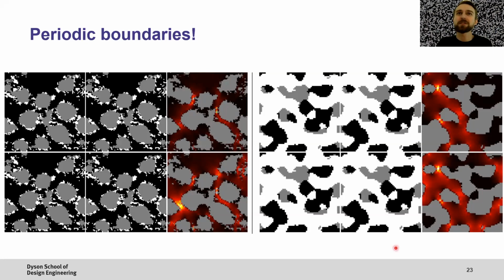So you can just about see, to those who have looked at flux maps before, the top is with the boundaries. In all cases, this is the same microstructure, okay? These 6 are the same microstructure. And I put a matrix of them so you can see that what comes off the right appears on the left and what comes off the bottom appears on the top. I'm doing a conventional diffusion simulation from top to bottom. And in the top simulation, I've got conventional boundary conditions. There's a mirror here and a mirror here. But in the bottom one, I've got this periodic system turned on, which has now been implemented in TauFactor. So you can run this yourself. And now you can see that the paths, which are particularly active for flux, are different, okay? And so this one used to be not very bright, and it's now very bright indeed.